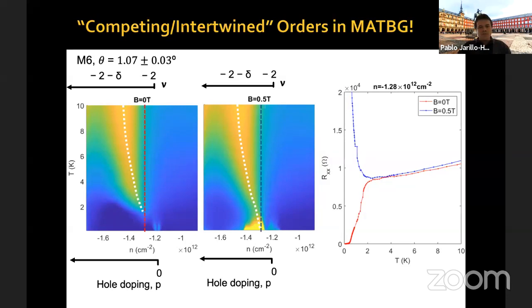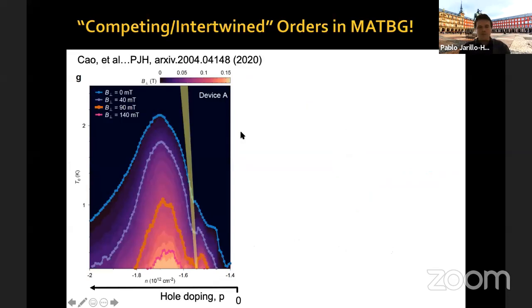So there seems to be something which is competing with superconductivity when you're a little bit off from the correlated insulator state. And that something which is competing with superconductivity has a resistivity maximum which evolves in this temperature versus density phase diagram.